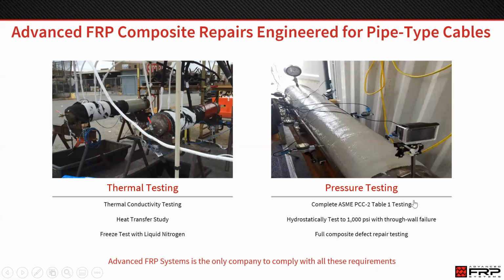Some of our clients use liquid nitrogen to freeze the dielectric fluid inside of these lines in order to do internal repairs of the conductors. So we wanted to ensure that they would still be able to freeze the dielectric fluid, and that freezing with liquid nitrogen at below minus 300 degrees Fahrenheit, thermal shock wouldn't damage the pressure capacity of our carbon fiber repair. So we did those thermal tests.